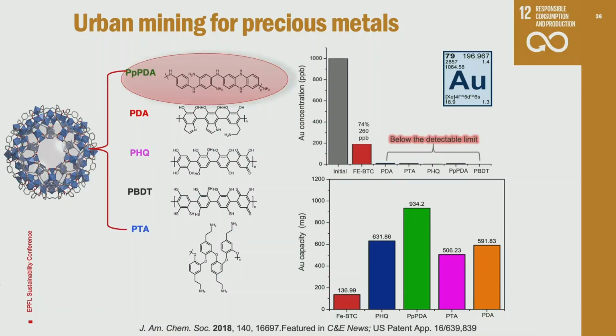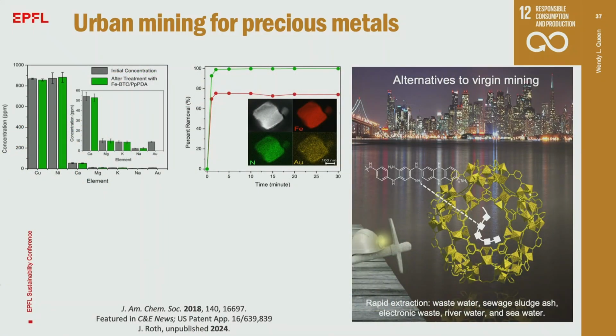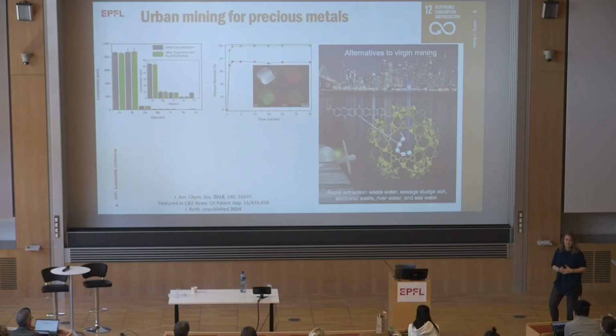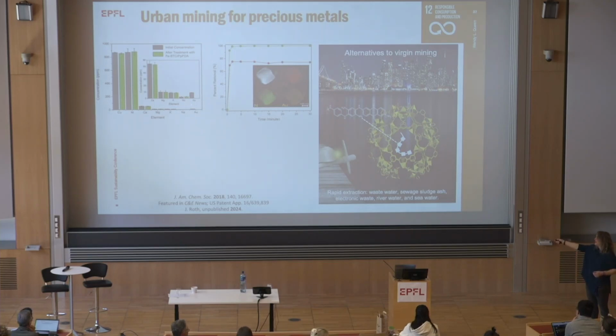This particular material, we call PpPDA, has a really high capacity. So the material can absorb around 1 gram of gold for every gram of material. Okay, so that's extremely high. It's also very fast. So we began testing it, again, in very complex matrices. So here you see a liquid containing many ions. We've spiked it with small concentrations of gold, around 10 parts per million, and huge concentrations of copper and nickel, around 850 parts per million, because these are often prevalent in electronic waste. What we note is that in green, we remove all of the gold, at least within error of our experiment. We leave behind the other metals. So we're quite happy with these materials.